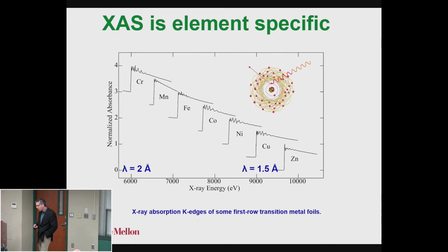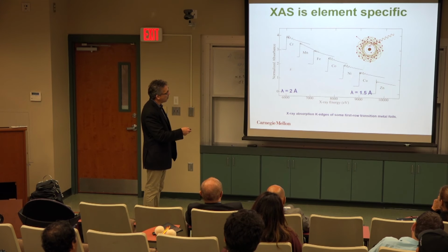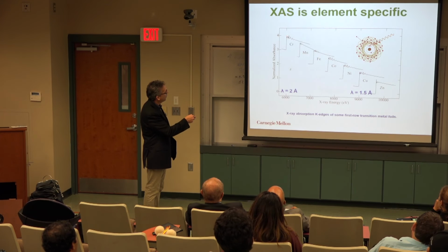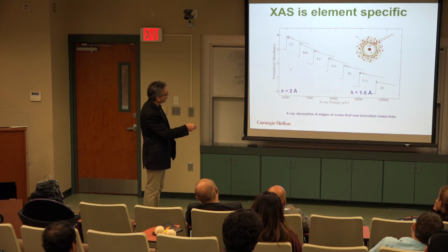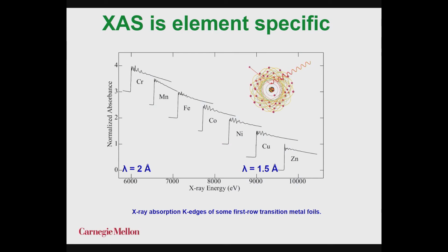So this is an important piece of X-ray absorption spectroscopy, okay? It is metal specific, okay? So what this is showing you is the absorption of chromium, manganese, iron, cobalt, nickel, copper, zinc. And this is the energy, right? So the X-ray energy for chromium, somewhere around 6,200, it's gonna jump. And I get the XANES region, and I get the EXAFS region. And it's not until all the way out here that I start to get manganese, which of course is the next one in the periodic table.